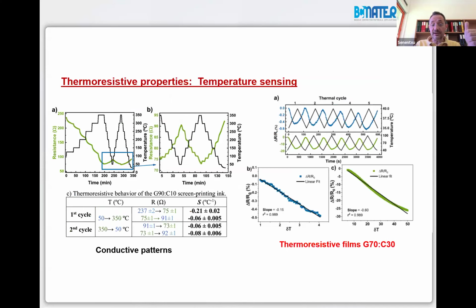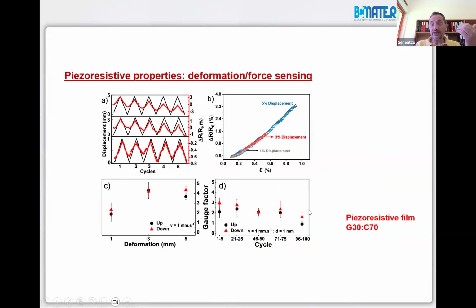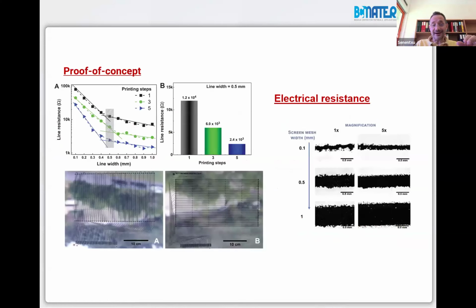So we have the conductive tracks, but also if we go to reduce from 90 to 70% of graphene just for the active layer, what we have there is a very beautiful thermoresistive sensor that can perfectly measure temperature variation in a linear way. But if you go even lower, only 30% graphene, you have a piezoresistive sensor. That means variation of the resistivity also in a linear way, up to 5% deformation, with the same system. So a huge contribution to sustainability based on basically carbon and water.